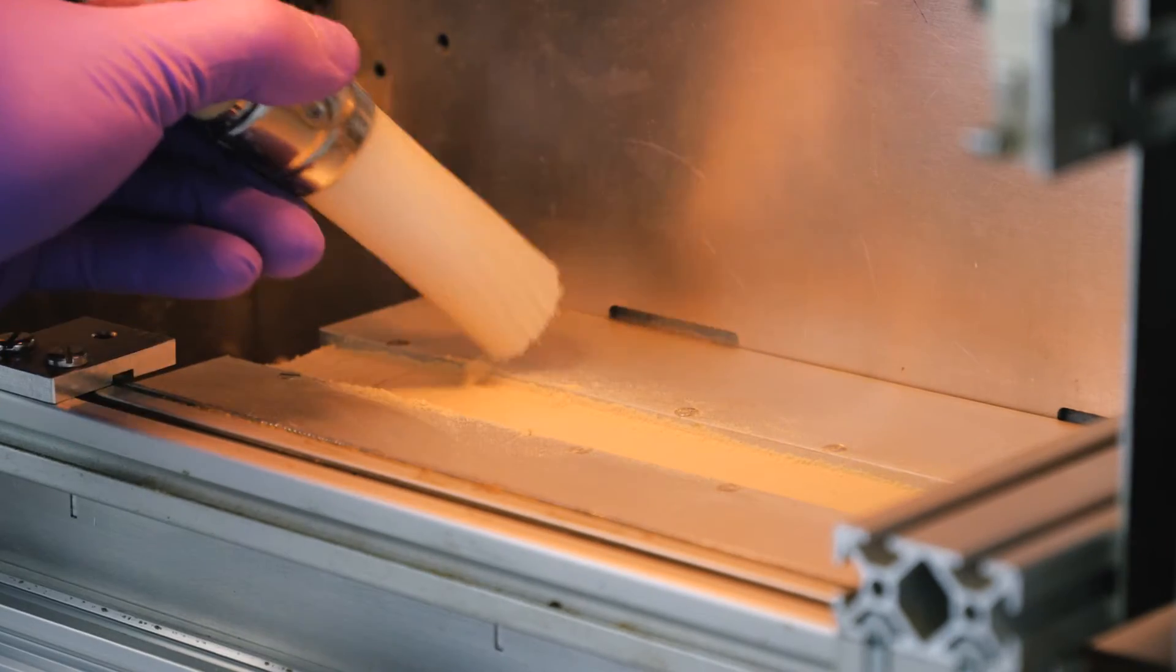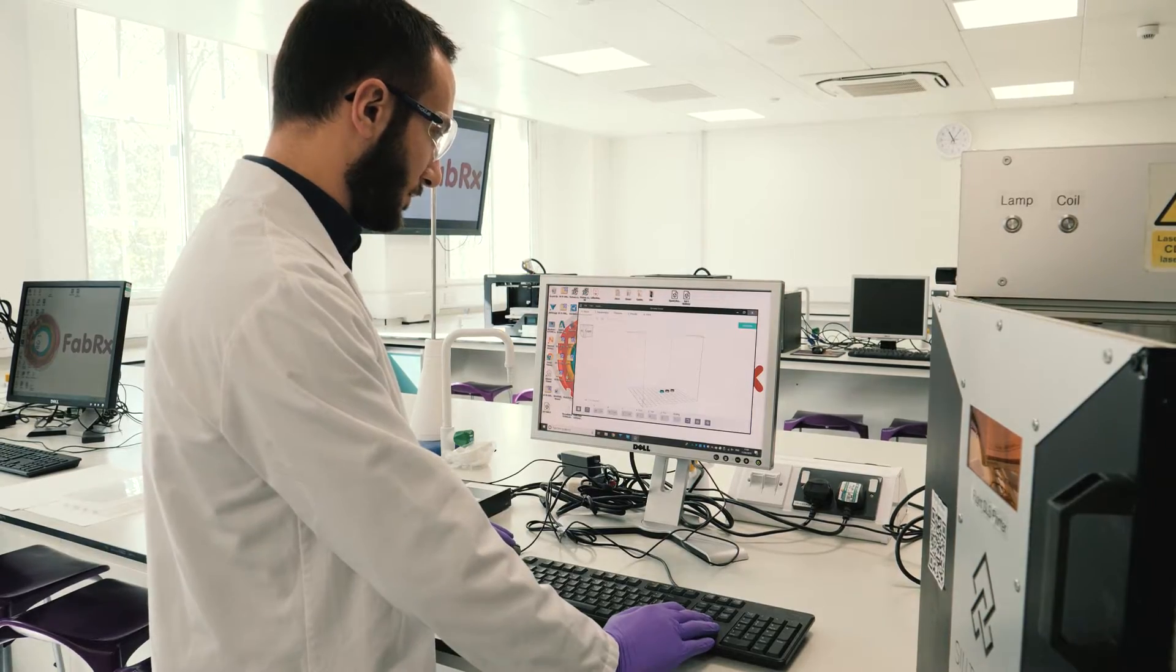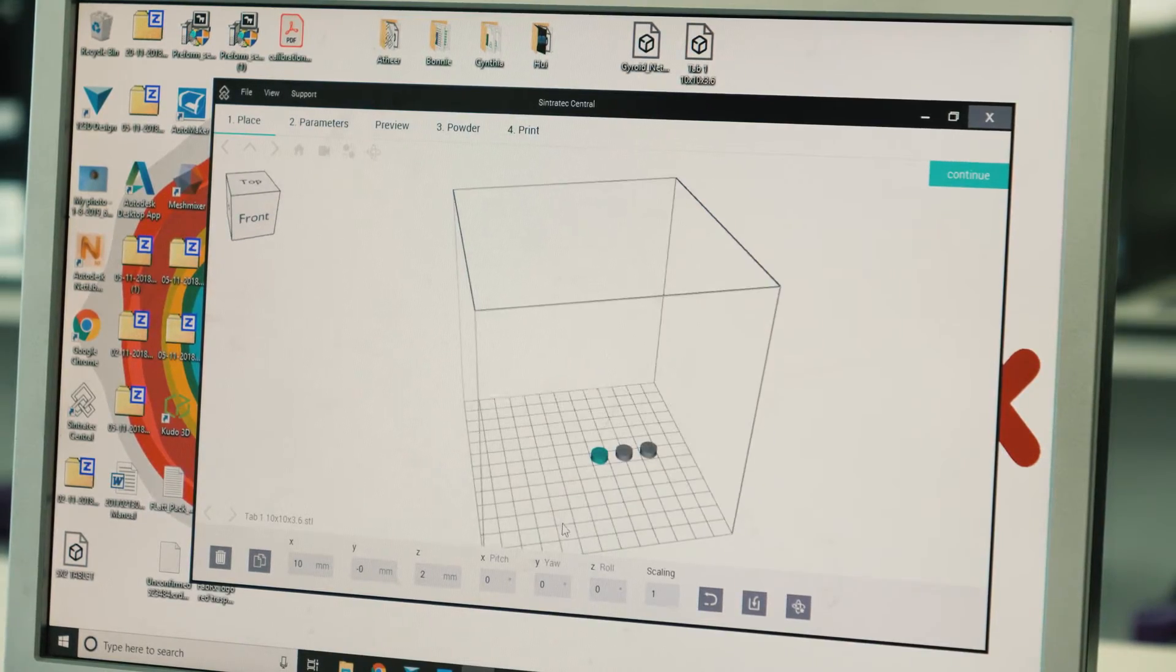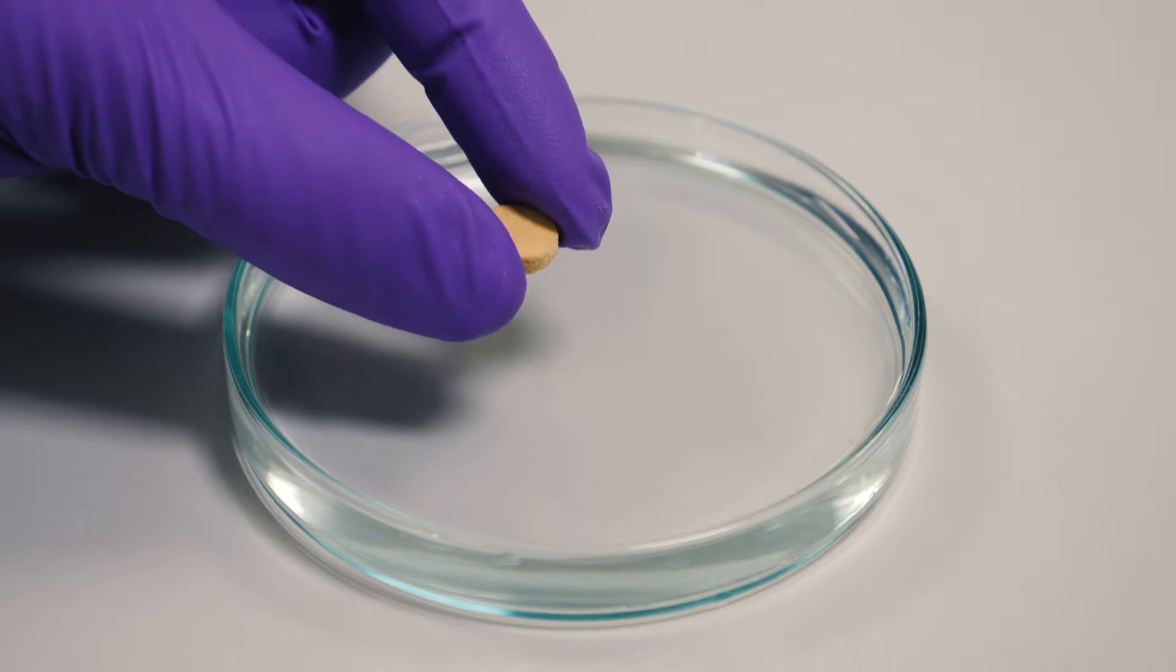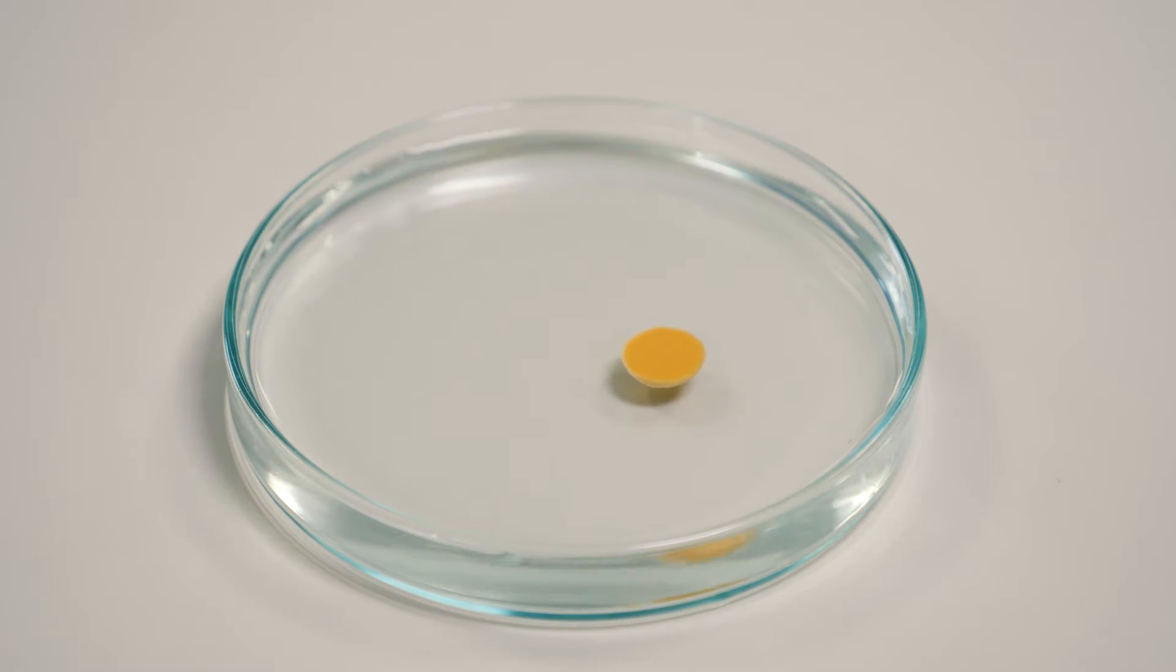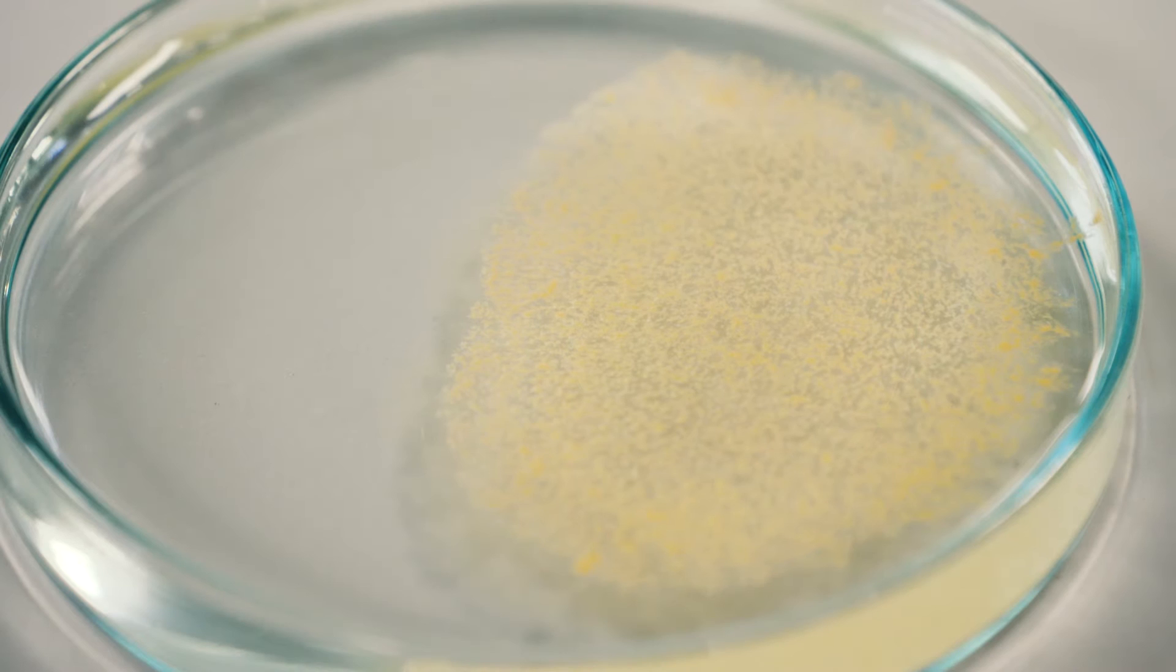We bought our first Sintratec kit and then we tried to print the first tablets using Paracetamol and we managed to print them. So we dissolved those tablets, we checked the amount of drug inside and surprisingly we realized there was no drug degradation, the drug was still there and it was a very happy moment.